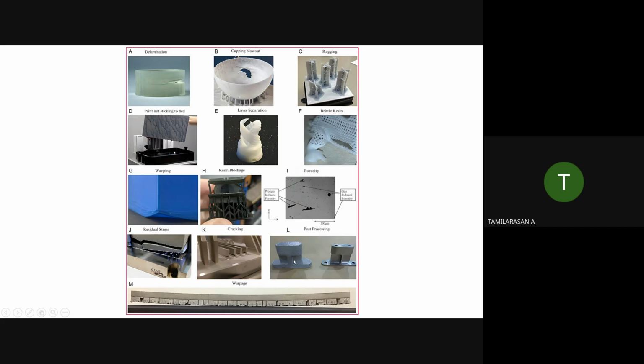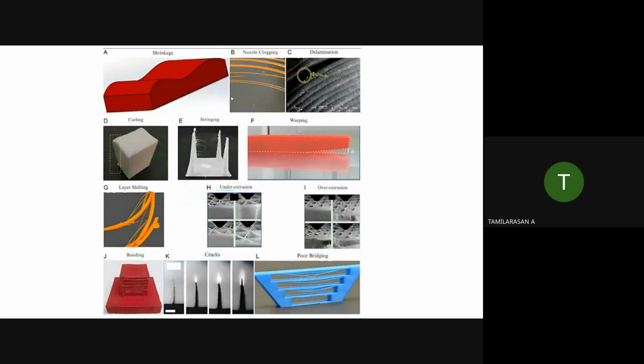And for cracking, post processing is needed. These are some of the common defects which exist. Then apart from that, further we see shrinkage and nozzle clogging sometimes, and delamination and curling, then warping. So many kinds of things exist, last row banding, cracks, and poor bridging. See why this happened, because of the temperature and so many factors, as we already discussed in our previous session, and already learned from our theory, the printing process parameters.